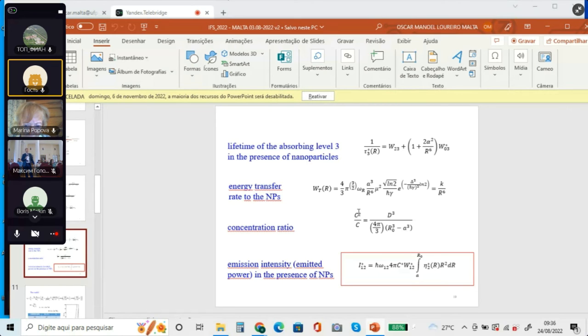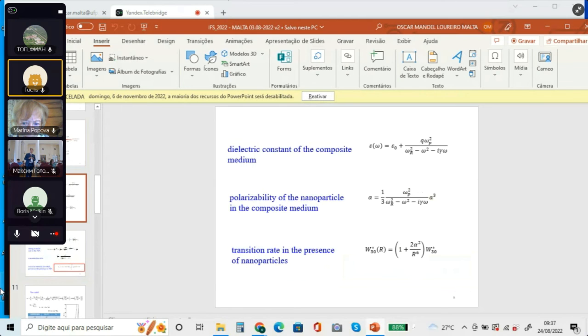But we have to guarantee in our samples, with and without metallic nanoparticles, that the number of emitting species is precisely the same, because we will compare emission intensities in different samples, you see? So we have to be very careful. We have to guarantee that the number of emitting species is the same in both samples. And the concentration is taken into account mainly through the filling factor, which appears here.